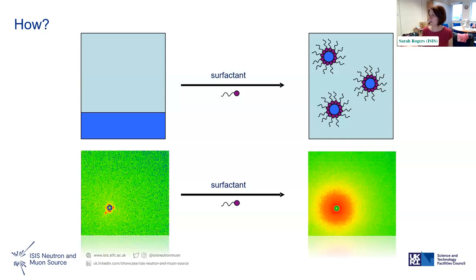So how do we do that? Well, as I said before, we have a bespoke pressure cell. We pressurize the CO2. We have a special injection system that allows us to pump in water and a surfactant. And what we do here is we use heavy water, D2O. There's a very clear scattering signal from the D2O that we can see from the CO2. So it allows us to see if these nanopools of water are actually forming or not.